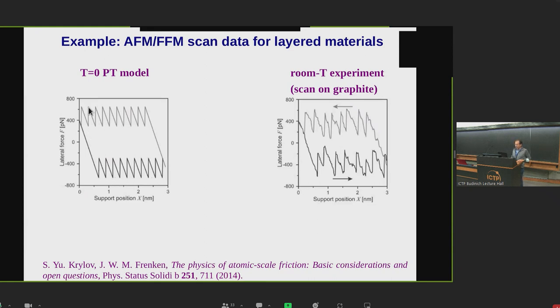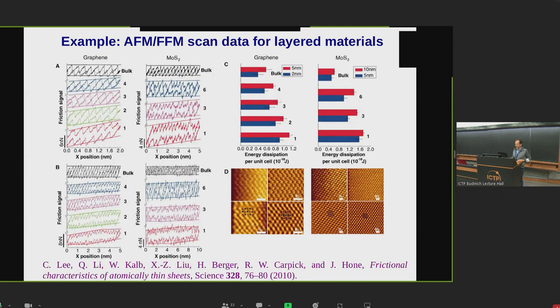The Prandtl-Tomlinson model at T equals zero will give you a perfectly periodic sequence of jumps and stick-slips. In an experiment, which is always carried out at finite temperature, these stick-slips are not completely regular. They are also affected by noise. Temperature will have the effect of slightly anticipating slips due to thermal jumps across the barriers. This is another example on graphene and molybdenum disulfide with different number of layers.